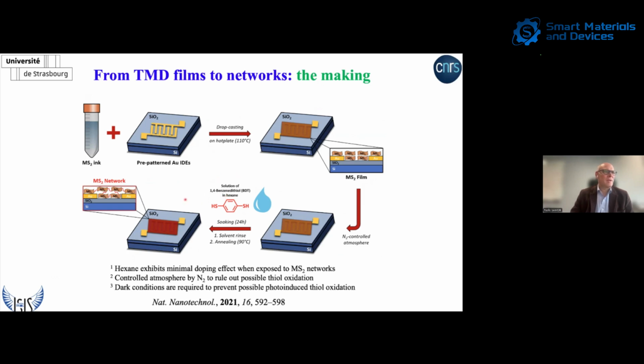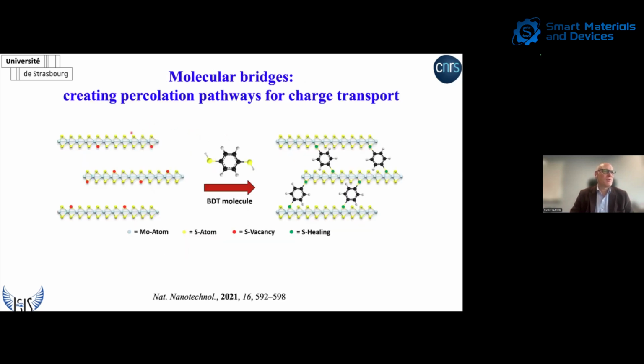Now, doing this, we create the one that I call network, where the nanosheets are linked between them. And so let's say this is a picture to show you what we have been doing. Essentially, we have been connecting adjacent nanosheets. I skip the whole characterization part, demonstrating that this network formation really took place. This has been monitored by Raman spectroscopy, and by XPS in particular.